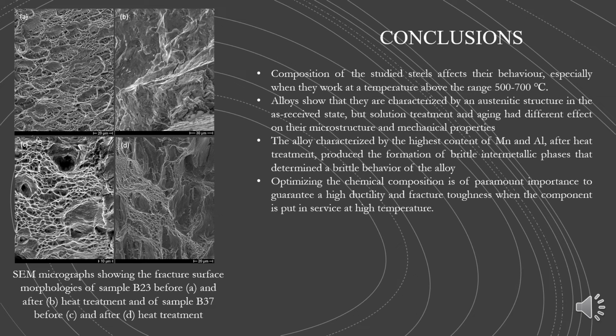Finally, the same analysis of the fracture surfaces of B23 and B37 shows that B37 shows a ductile fracture before and after heat treatment, while B23 shows a brittle fracture characterized by transgranular fracture with secondary microcracks.